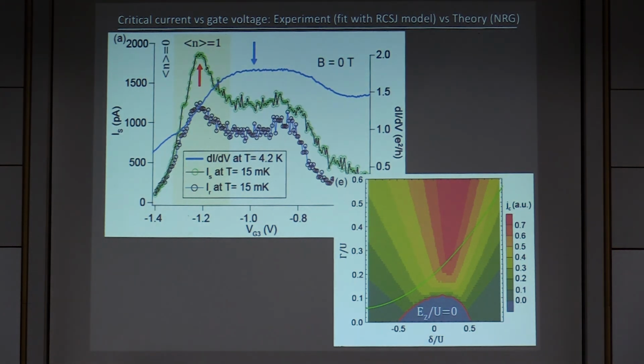So now, to conclude, I want to show you what happens in the two more minutes, one minute. What happens, and I cut down my presentation, but what happens in the superconducting regime? It's one important message I want to leave you. So in the superconducting regime, we have this localized spin coupled to a superconductor, and let's see what happens when we apply magnetic field.